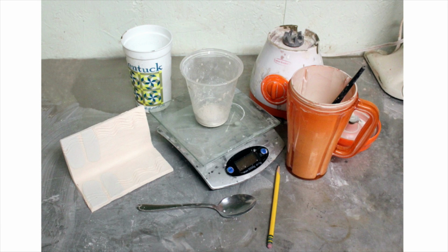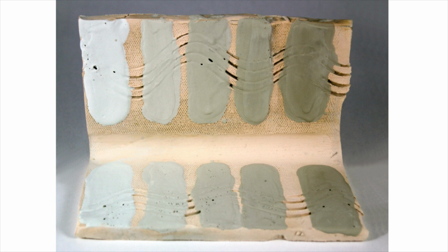Then add another 10%, which now makes it a total of 20% of the influence ingredient added to that mixture. Mix thoroughly and brush on a stripe of that mixture. Then add another 10%, which now makes it a total of 30% of the influence ingredient. Mix thoroughly, brush on a stripe of that mixture. And lastly, add another 10%, which now makes it a total of 40% of the influence ingredient added to the base glaze.